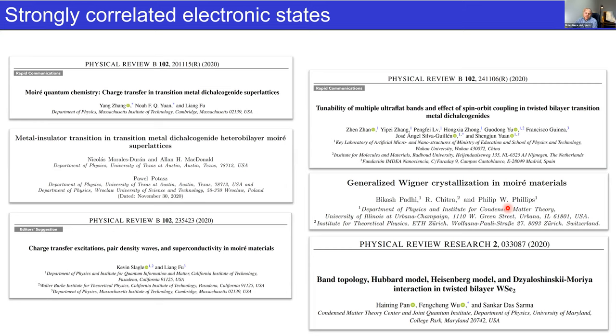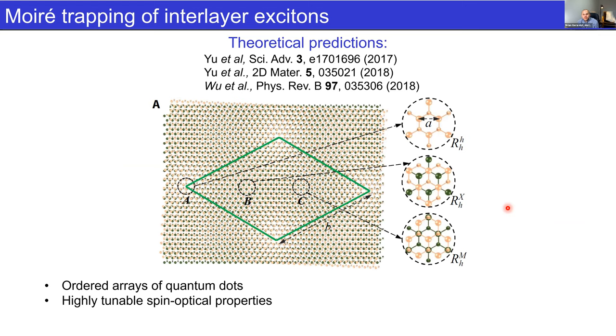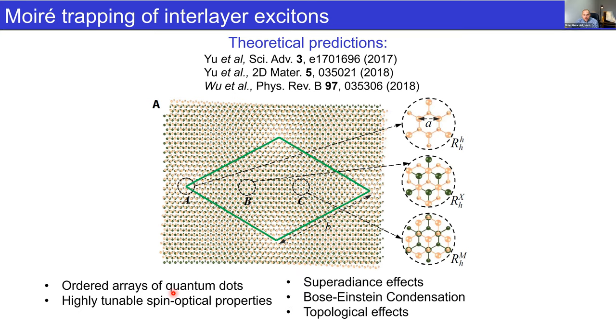So in addition to the strongly correlated states that one might imagine, there are also predictions, in particular from Wang Yao and from Allan MacDonald, that the Moiré superlattice could provide strong trapping potentials for the realization of quantum emitters. In principle, one should end up with carrier confinement at these different atomic registries, which act as trapping sites, the high symmetry points in the lattice, and these properties should be highly tunable. So we should end up with something akin to ordered arrays of quantum dots with highly tunable properties, and perhaps a high density of indistinguishable emitters that could lead to things like superradiance effects, Bose-Einstein condensation, or topological effects. So it's again a very rich platform to explore optically.